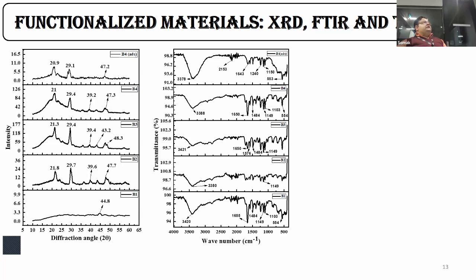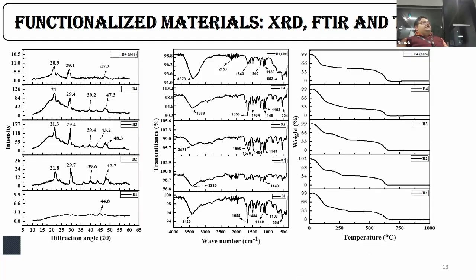We also carried out analysis with FTIR, and various functional groups were observed in this case, as well as TGA structures. The reason for doing FTIR is to ascertain whether the functional groups lie in a stretch from 3,300 till 1,240, and the lower peaks ascertain the distribution of different functional groups like hydroxyl groups, sulfone groups, the aniline structure, and the dopant, that is lauryl sulfate, which is present.